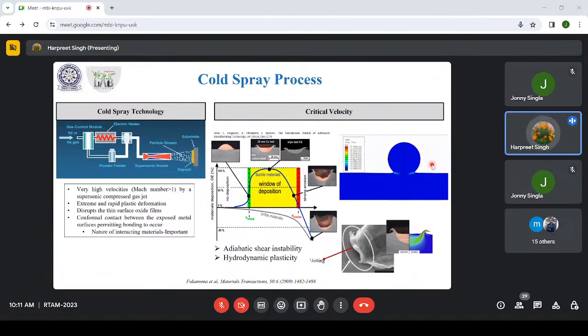Now, another thing to be noted here is that the temperature at the interface is increasing. You can see this: the temperature at the interface of the particle and the substrate is increasing. This is good for us, for this jetting phenomenon. So what happens when this localized temperature increases? This is very localized to the interface of the particle and the substrate, right? And let me tell you, all these things are happening in a very minor amount of time, much less than 1 second, because the standoff distance is typically very low, 40 mm or so in cold spray. That's why we call it a severe plastic deformation process, an extreme and rapid plastic deformation process.